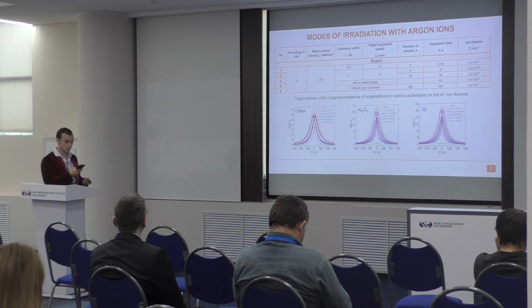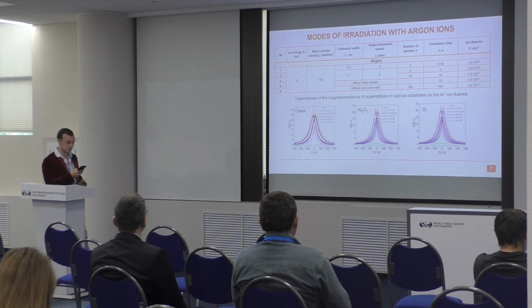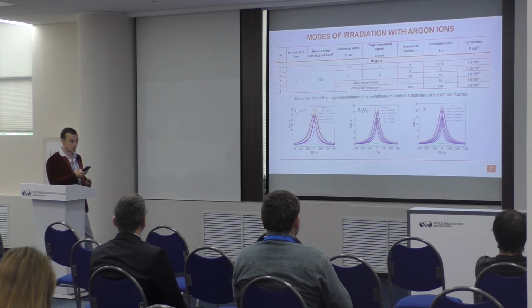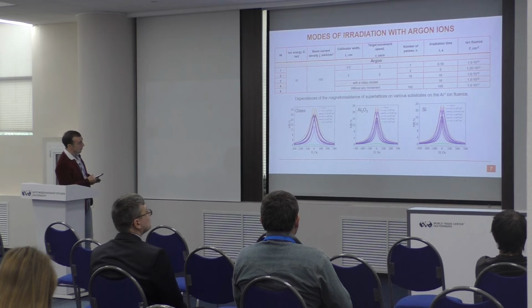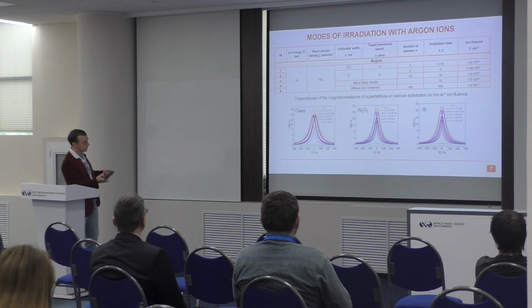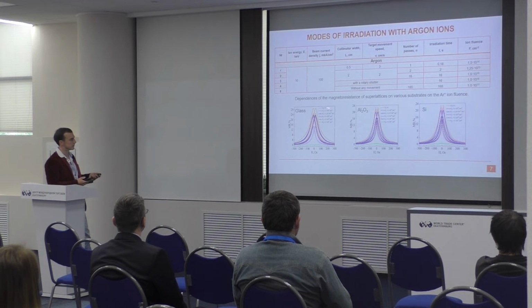This slide shows the modes of irradiation with argon ions. As a result of the magnetoresistance measurements, it was found that irradiation of superlattices with argon ions leads to a decrease in their magnetoresistance for all three types, regardless of the substrate material, at a fluence of ions on the order of 10^14. I'm sorry that these graphs are very small, but I will show you with the laser pointer.